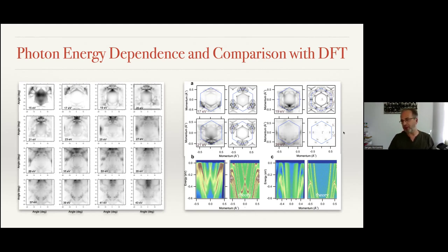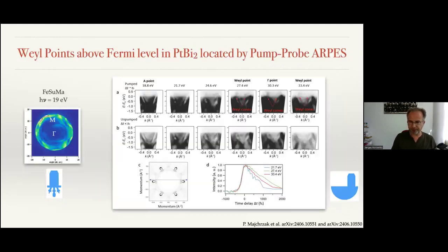There is a certain degree of similarity. We found the gamma point, the A point, high symmetry points. This is how the momentum-energy cuts look like; they are really similar. There are always some deviations between the calculated band structure and the experiment, we got used to them, but this is very helpful because we can identify these bands anyway, and we know which feature is responsible for which calculated feature. So this is experiment, this is theory, this is experiment, this is theory.